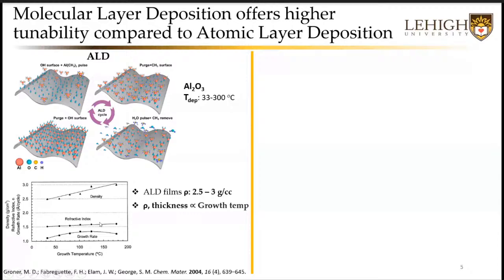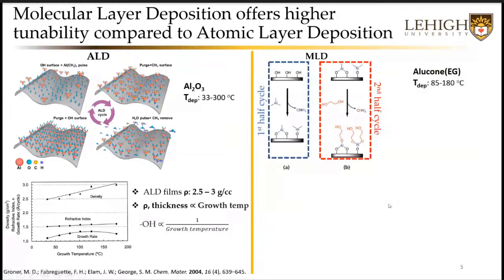And all this happens because the hydroxyl incorporation inside the ALD films decreases as the growth temperature increases. So the hydroxyl content in the films is inversely related to the growth temperature. Whereas MLD is a temperature sensitive technique. It could be done from 85 to 180.